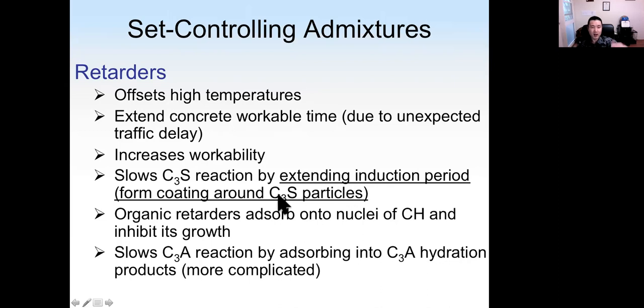So how does that work? The retarder is an organic material. It will form a coating around C3S particles, so the release of the ions will be slowed down because of this coating. Organic retarders also adsorb on nuclei of calcium hydroxide, so it will also slow down the growth of calcium hydroxide.